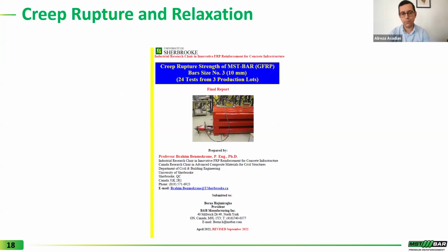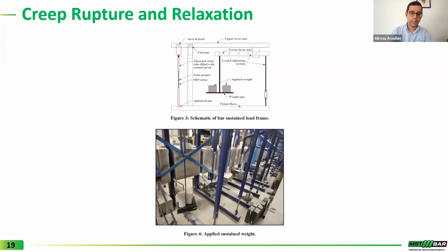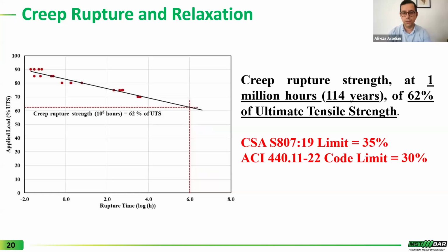Another concern with GFRP bars is creep rupture, or the effect of creep over the long term on the rebar. Again, we have done many tests at the University of Sherbrooke with Professor Brahim Benmokrane. So in this test, the rebar is under different levels of sustained stress, and then the time to rupture of rebar under each stress level is measured or recorded, and then the experimental data is extrapolated to see the creep rupture limit for MST bar or any other GFRP bars.